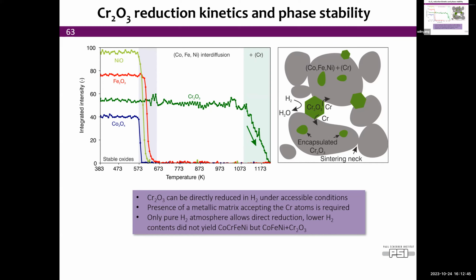And at the end of the day, you end up with a full reduction of chromium oxide, unless, of course, as the sintering also takes place, unless your chromium oxide becomes encapsulated by a sintering matrix of the iron, nickel, cobalt. So we have kind of a competition between this hydrogen reducing the chromium oxide, and as long as it's exposed to the surrounding atmosphere of hydrogen, it can reduce, and then the sintering and shrinkage that happens may encapsulate the chromium oxide before it's reduced.